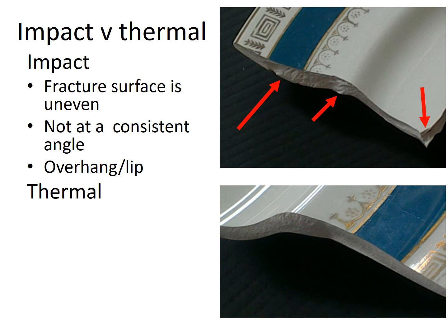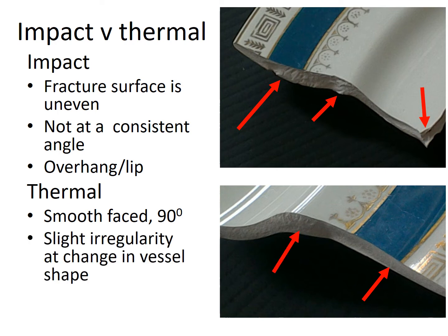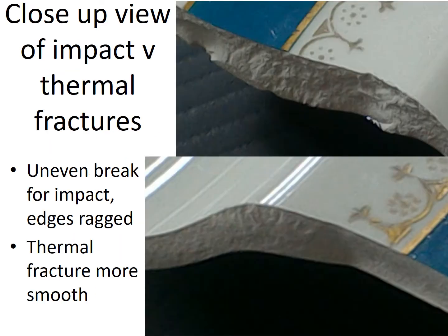In contrast, thermal fractures have a smooth surface and occur at 90 degrees to the plate surface and often at 90 degrees to the plate edge. The only unevenness occurs at the point where the ceramic body changes shape. The fracture is much cleaner than an impact break. So a close-up view of these fracture surfaces shows the ragged edge of the impact fracture and the smooth edge of the thermal break.